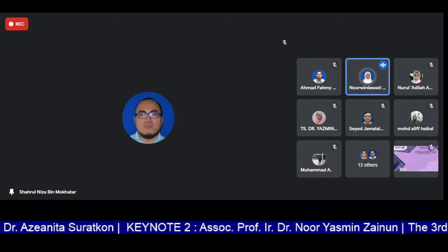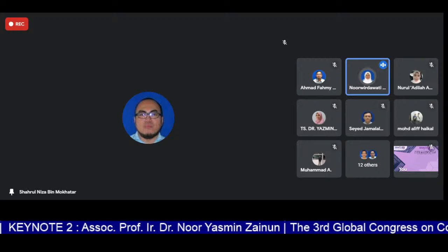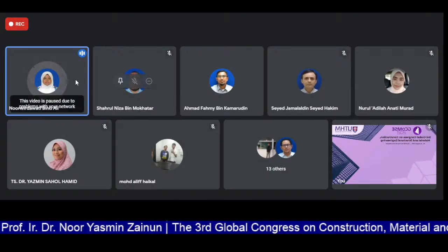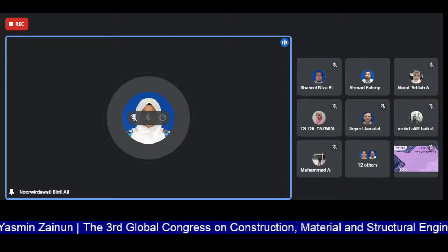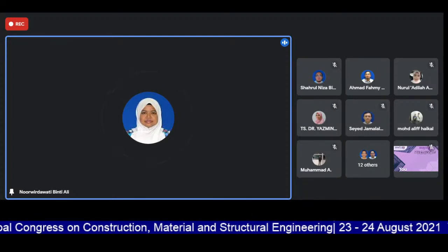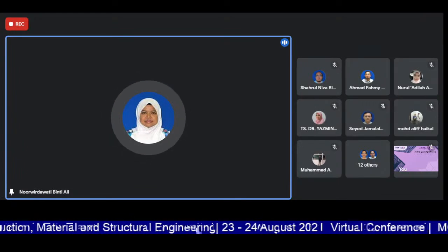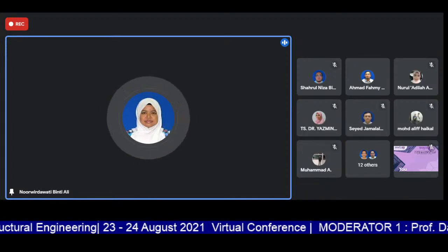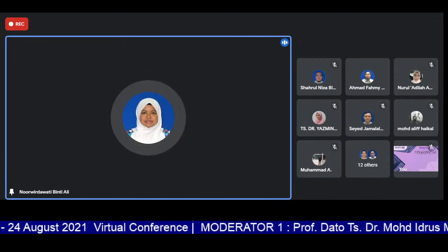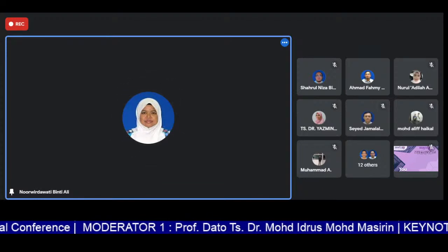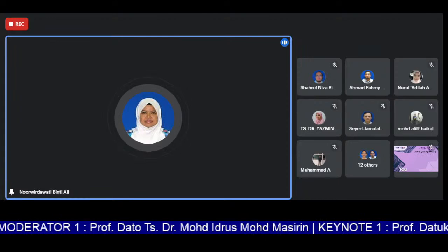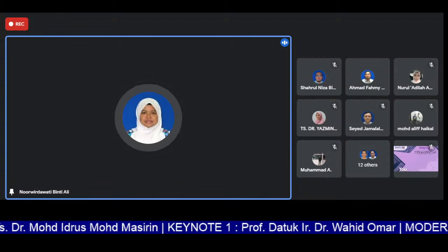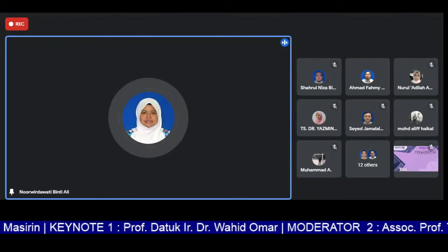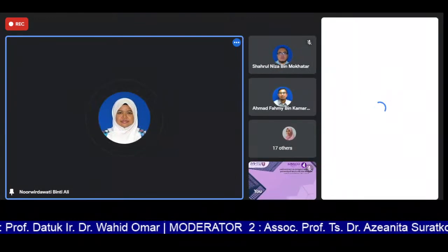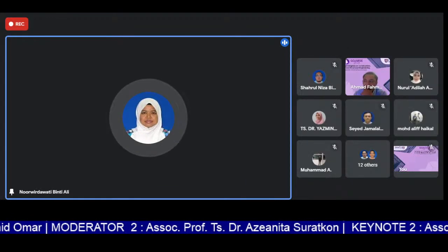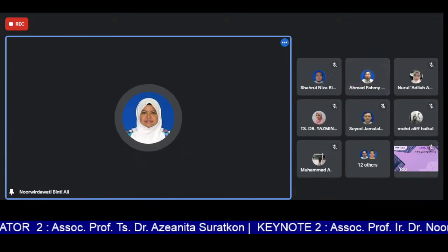Okay. From previous study, there is guidance on whether we want the opening to be a small opening or a big opening. In a previous study, maybe 2 years ago, we did a beam with a small opening, and we didn't see much effect on the beam's performance. Therefore in this study, we use a bigger size of opening, around 60% of the total area of the beams, and 60% we can group as a large opening.